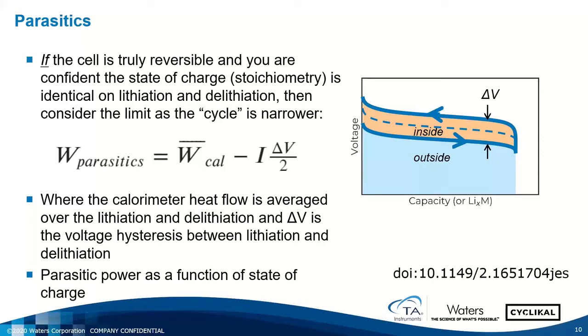If I average them, my entropy term cancels because one will have a negative sign, one will have a positive sign. And furthermore, I have to assume that I'm following the same path in composition space. But if I can confidently say this, then the instantaneous entropy term cancels, and I can take the average of my calorimeter signal on discharge and on charge, and I can take this delta in voltage, this voltage hysteresis, and say that half of it will correspond to the overpotential, and subtract that. So this would correspond to the overpotential power. So the entropy power has canceled out. I can compensate for the overpotential power, and the only thing that's left is now the parasitic power. So now I can get a measure of parasitic power continuously throughout my state of charge.